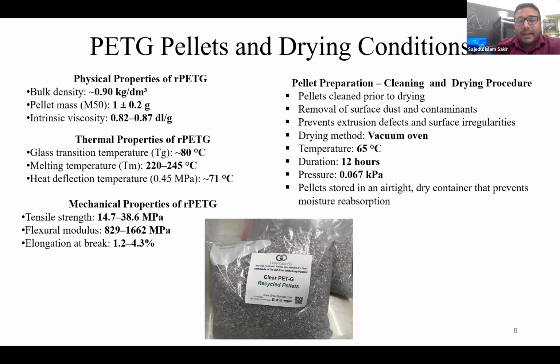And this is the PETG pellets, its properties and the conditions, how we dry it. So the PETG pellets have the physical property of bulk density 0.9 kg per decimeter cube. Then its mass and thermal properties. It's all coming from the PETG manufacturer, these recycled pellets. So we maintain a temperature between 220 and 245 degrees Celsius. Mechanical properties of the rPETG: its tensile strength is 14.7 to 38.6 megapascal, and elongation at break is 1.2 to 4.3%.